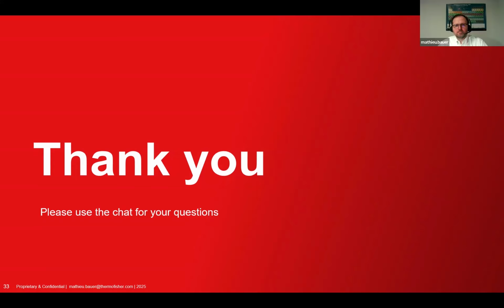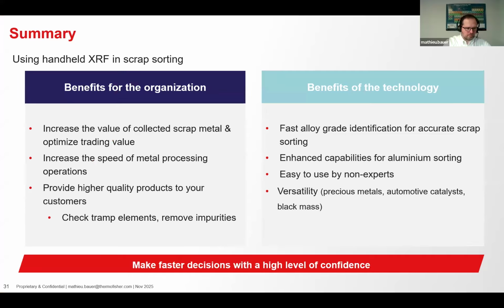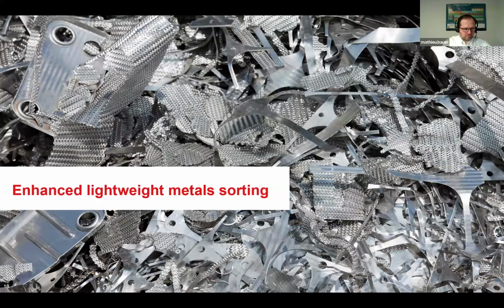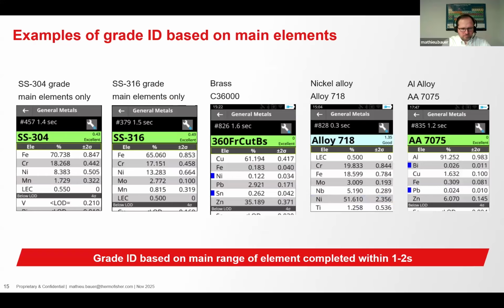Okay. And then last but not least, and this one, Matthew, you probably want to go back to slide 14 just for everyone's benefit. How can the analyzer show aluminum in AA7075 without measuring it? So we are using the scatter produced by the spectrum. A sample producing high scatter is a lightweight metal, and therefore we can make the assumption that it's aluminum without actually measuring the elements. In this way, we can accurately identify many lightweight metal grades within the aluminum family, about 3 out of 4, without measuring aluminum itself.